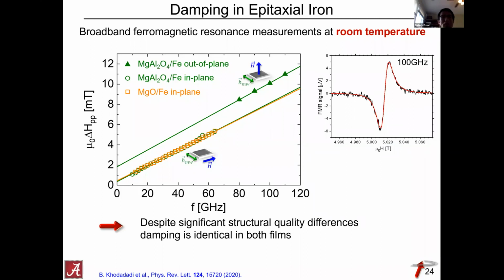So with the precessional orbit not being elliptical, more circular for the out of plane, you may end up having higher sensitivity. The zero frequency line width might be more sensitive to some kind of inhomogeneity. But I don't really quite understand how this works, but this is something that I have seen.